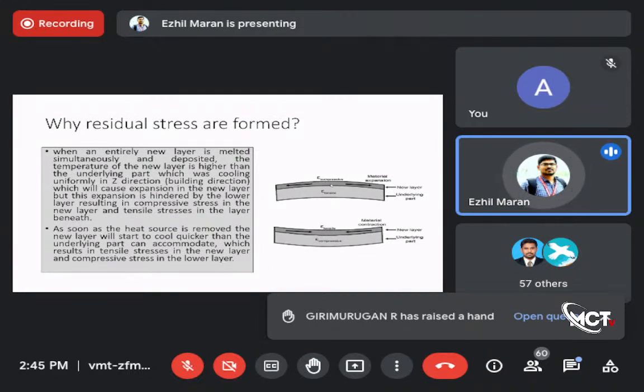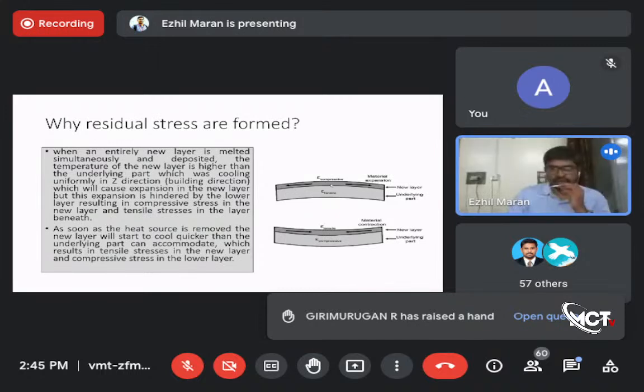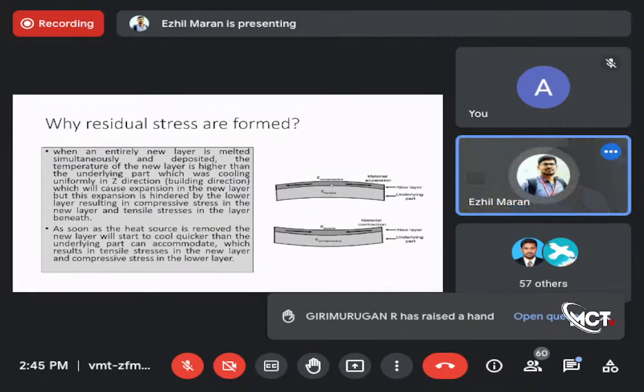The size of the previously deposited layer is now reducing because of contraction. So over that contracted layer, we are now depositing a fresh layer of metal, one more layer. Because of this expansion and contraction, this fresh layer tries to expand, but the already formed layer behind it tries to contract. This difference in expansion and contraction will create residual stresses.